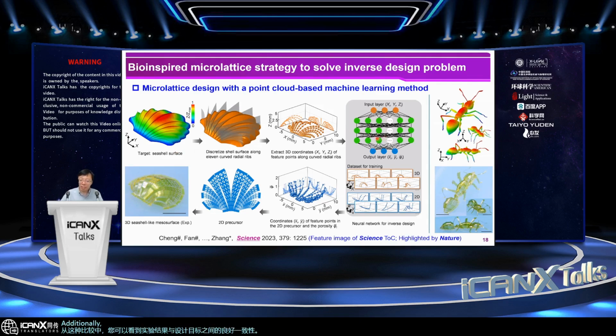Additionally, by discretizing the surface using a cutting strategy inspired by the CT scanning, we can use this machine learning algorithm to achieve the inverse design problem. And from this method, we can derive the 2D microlattice pattern and then use the 3D assembly to reproduce this surface. And in this specific example, we can use around 4,000 micro triangles and 8,000 micro ribbons to reproduce the surface at the millimeter scale.